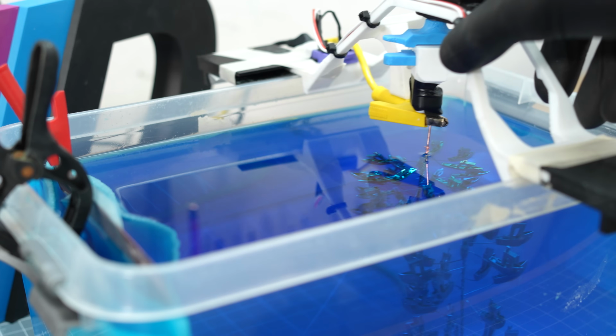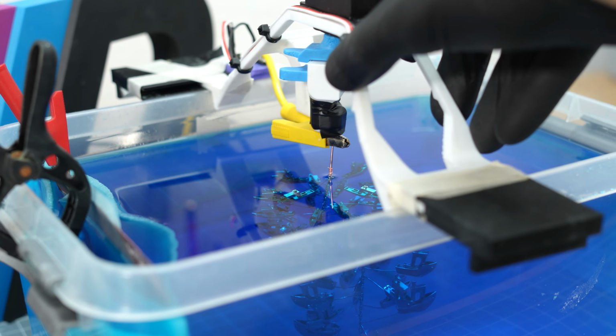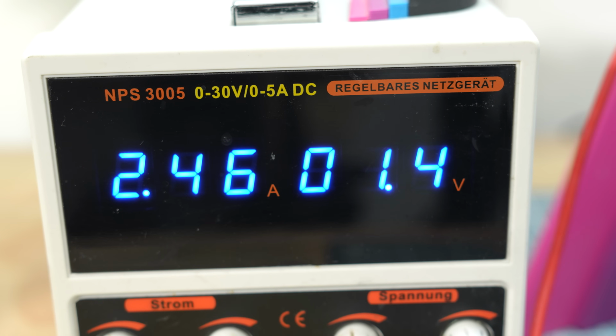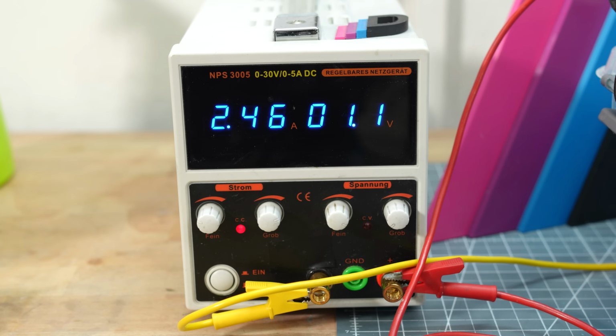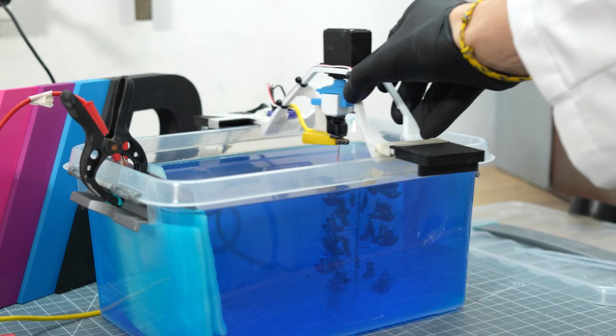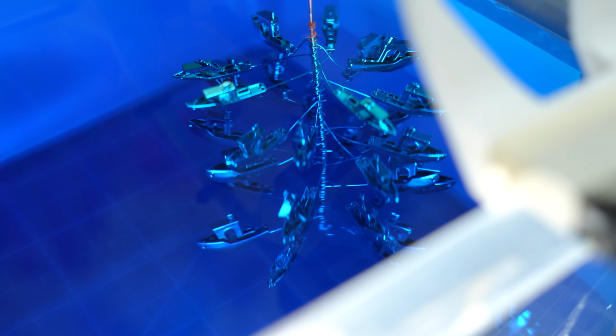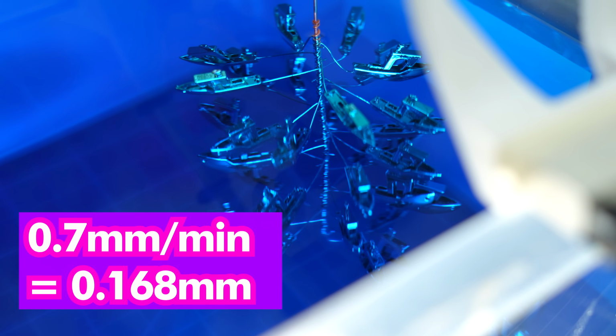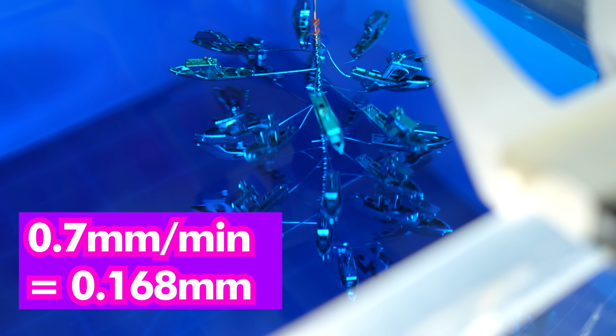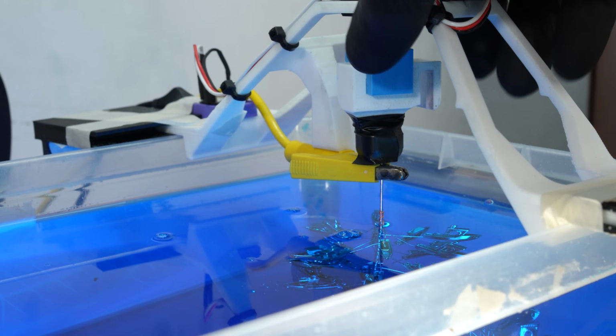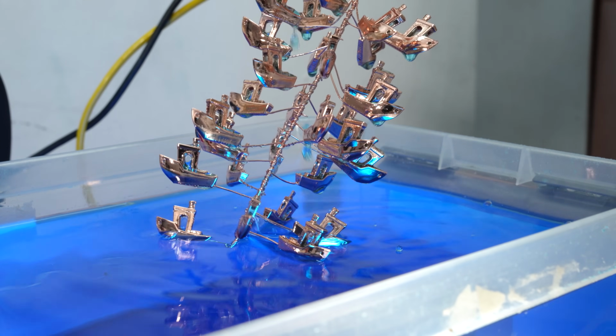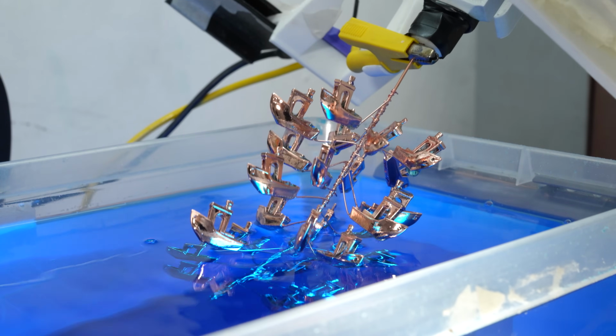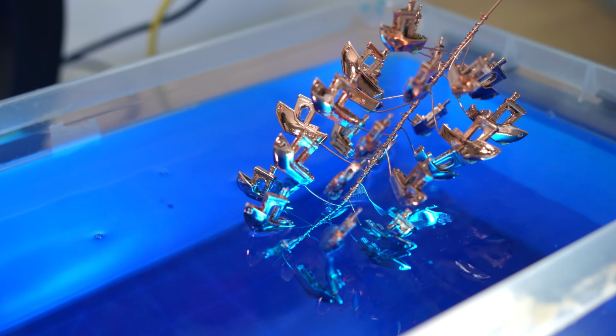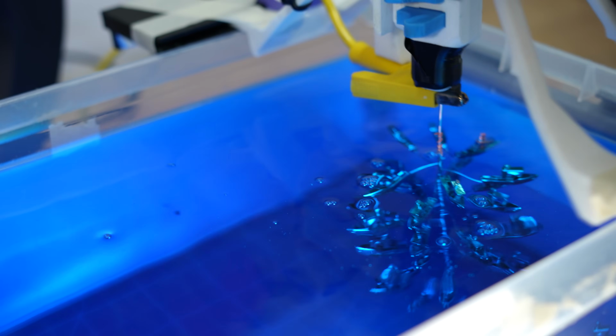Let me show you what it does. As I move the print closer to the anode, it decreases the voltage to maintain a constant current. This is crucial for a good deposition result. Let the benchies form a copper layer for approximately 4 hours. It's okay to check occasionally if everything is running smoothly, and you can see directly whether it's working or not. The copper shines extremely brightly.